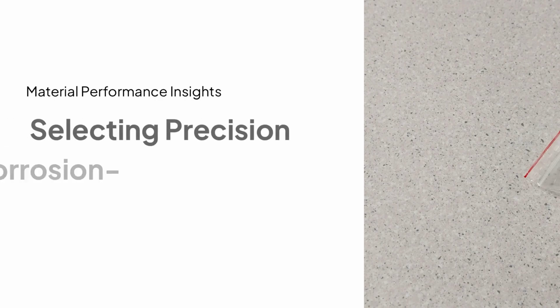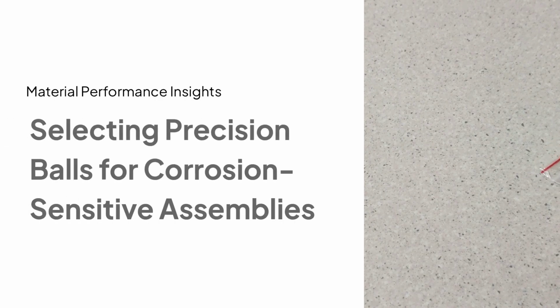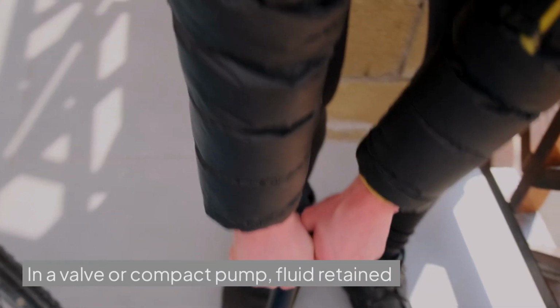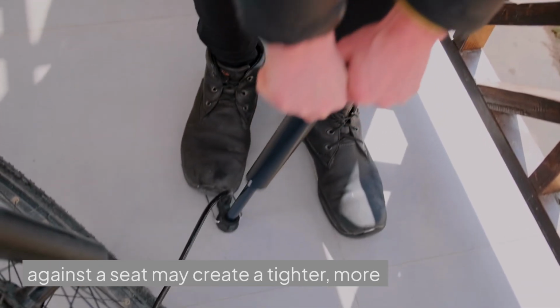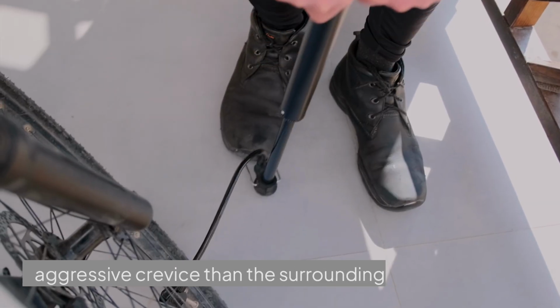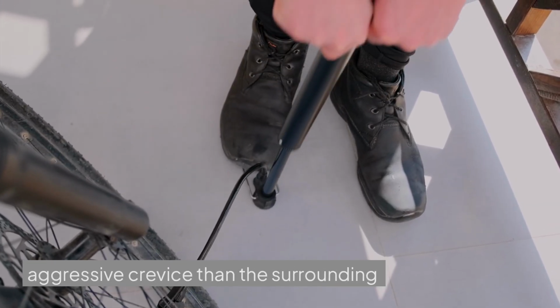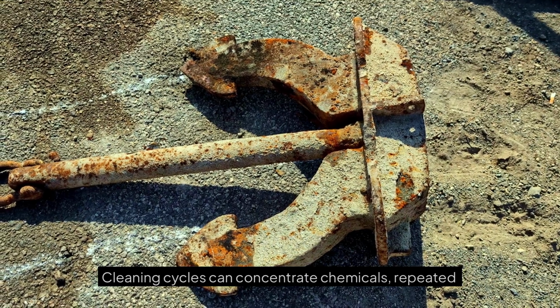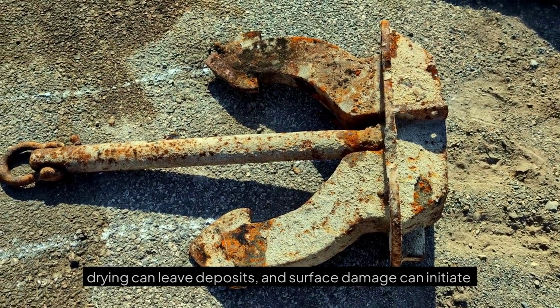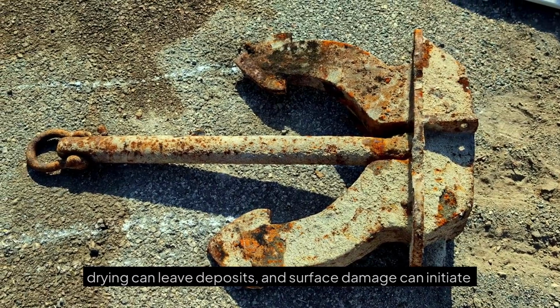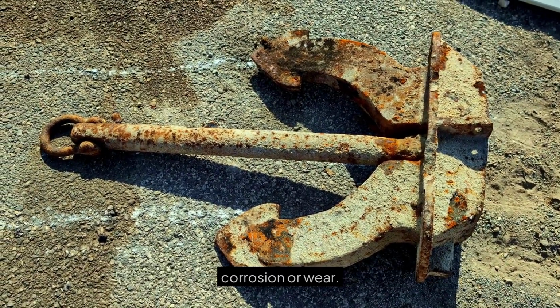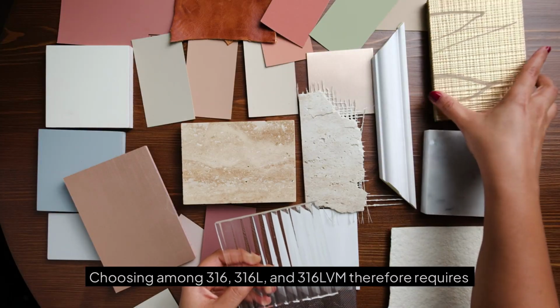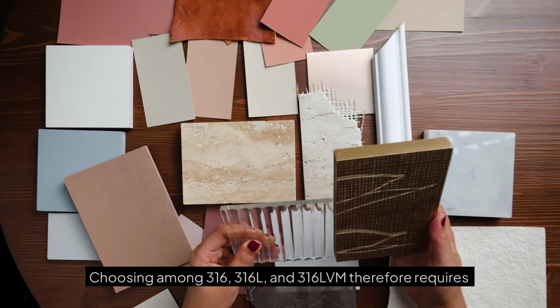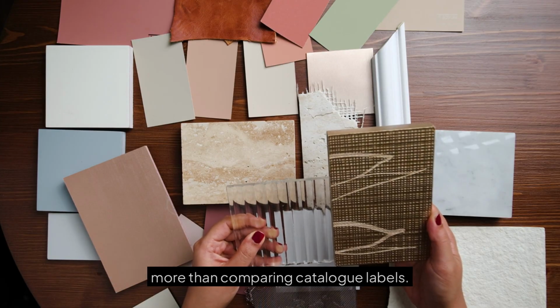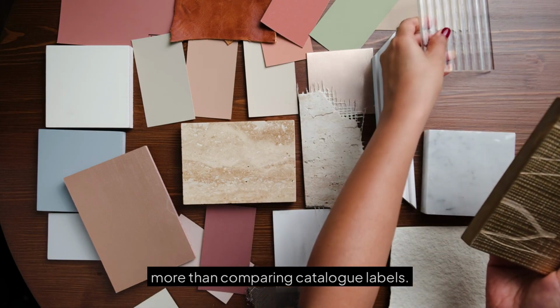A precision ball can carry the correct material name and still fail inside a corrosion-sensitive assembly. In a valve or compact pump, fluid retained against a seat may create a tighter, more aggressive crevice than the surrounding system. Cleaning cycles can concentrate chemicals, repeated drying can leave deposits, and surface damage can initiate corrosion or wear. Choosing among 316, 316L, and 316 LVM therefore requires more than comparing catalog labels.